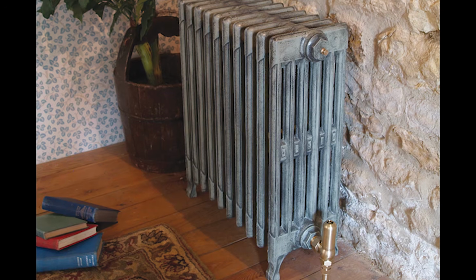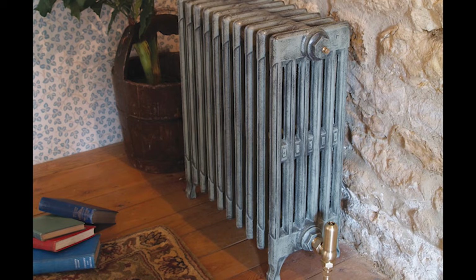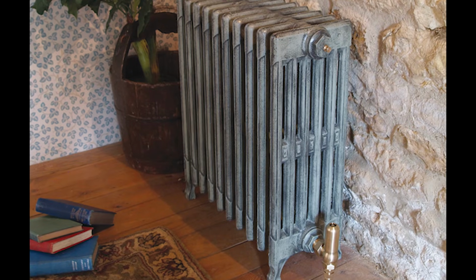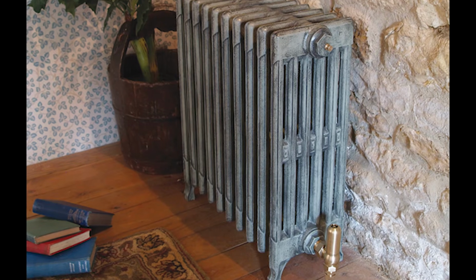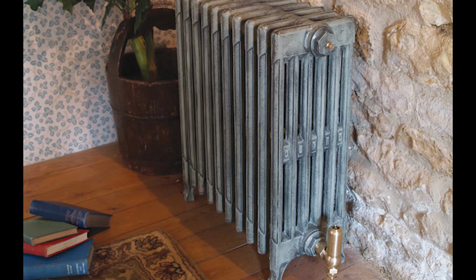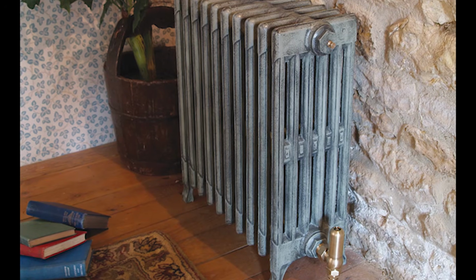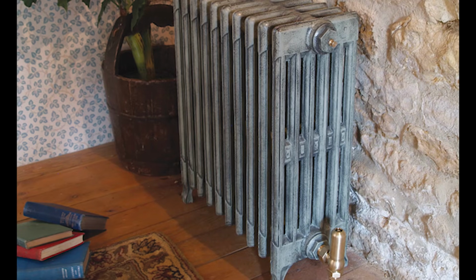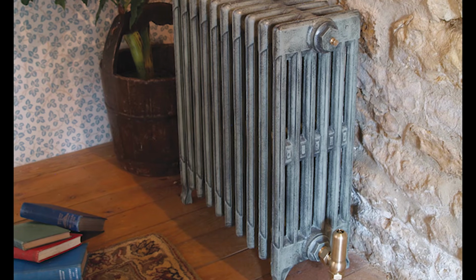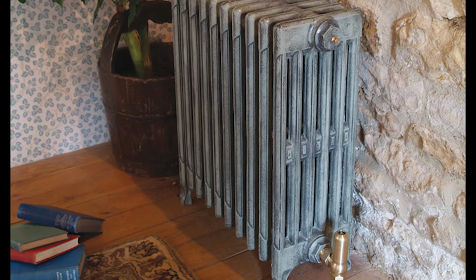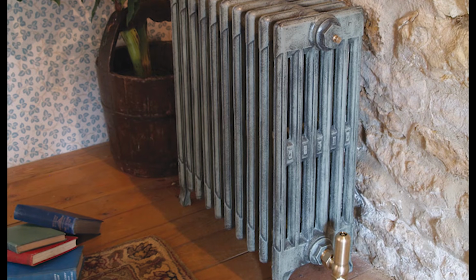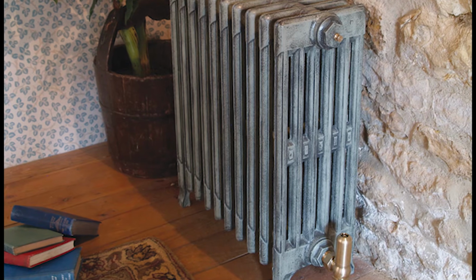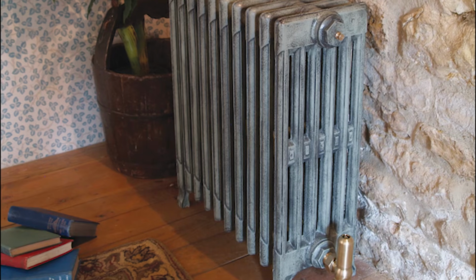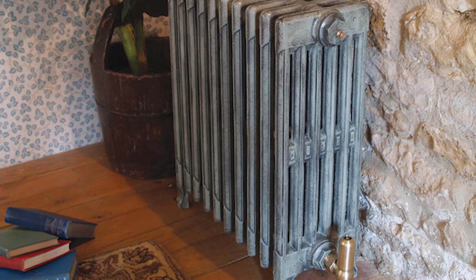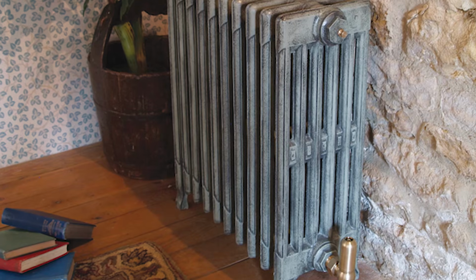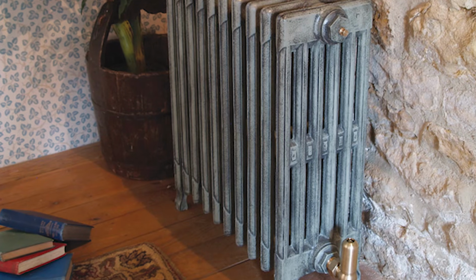The magnetite formation process required specific conditions that American low-pressure steam systems naturally provided. Operating temperatures between 210 and 220 degrees Fahrenheit, combined with the deoxygenated environment of a properly sealed steam system, created ideal conditions for stable magnetite layer development. The thick walls of cast iron radiators provided abundant iron for this protective film formation while maintaining structural integrity even if some base metal was consumed in the process.